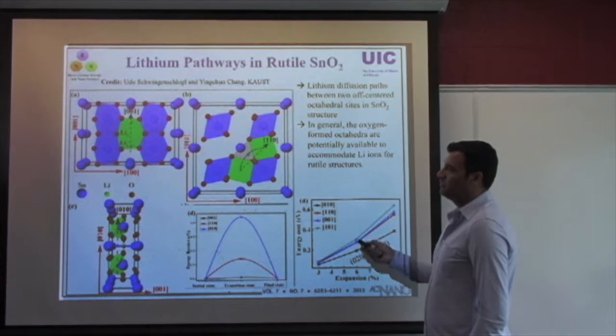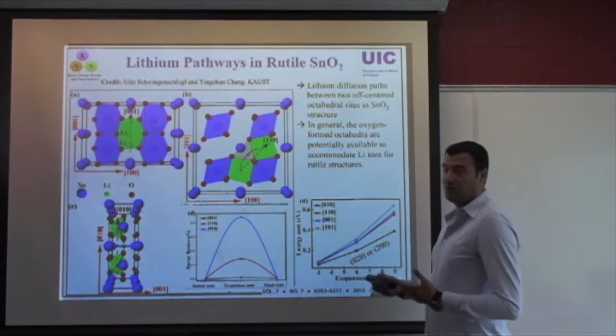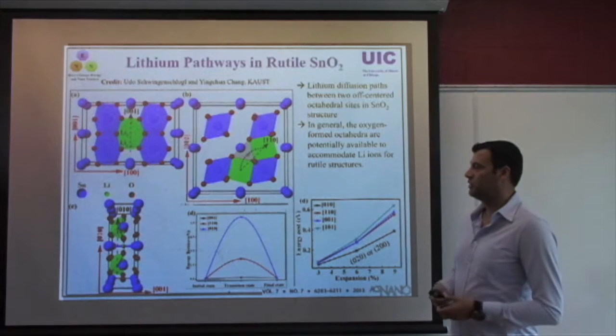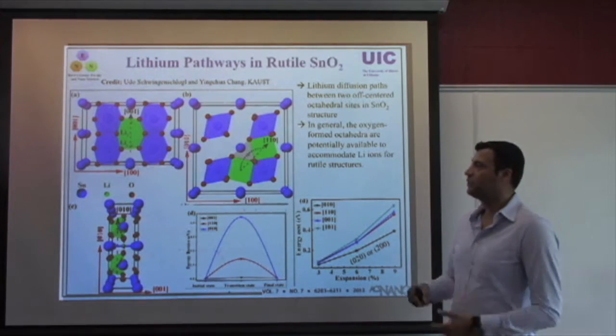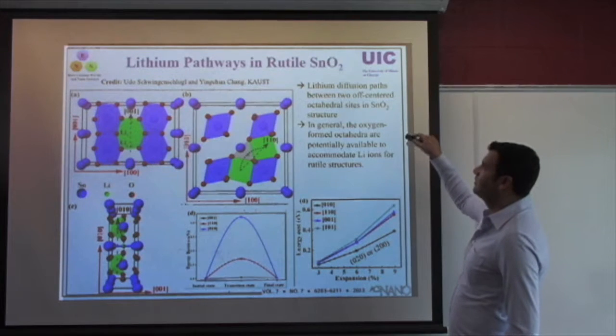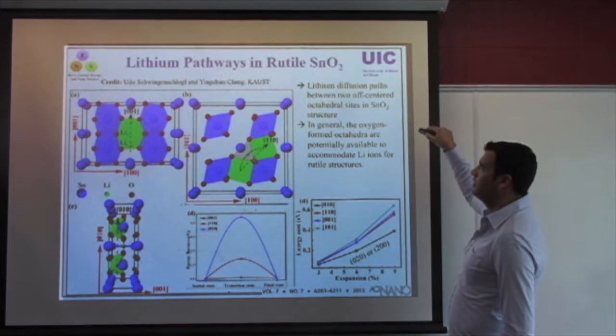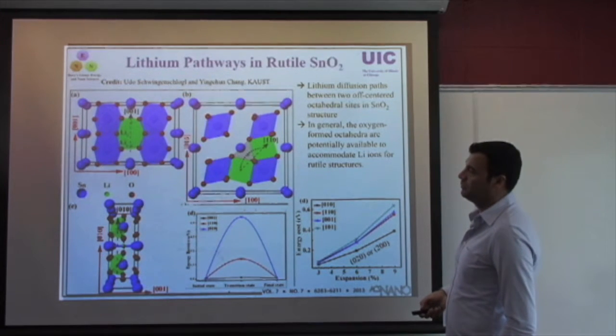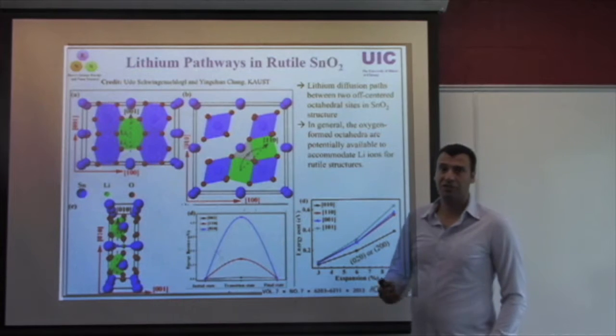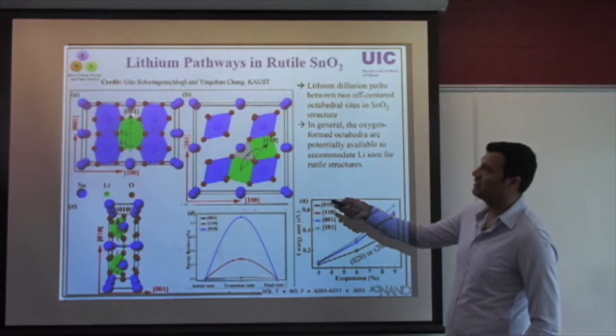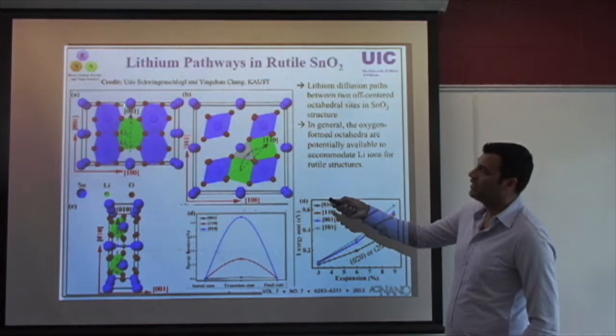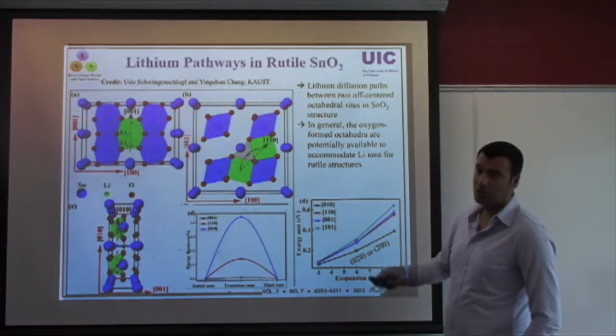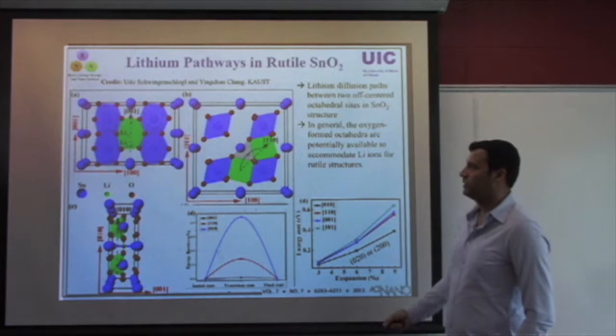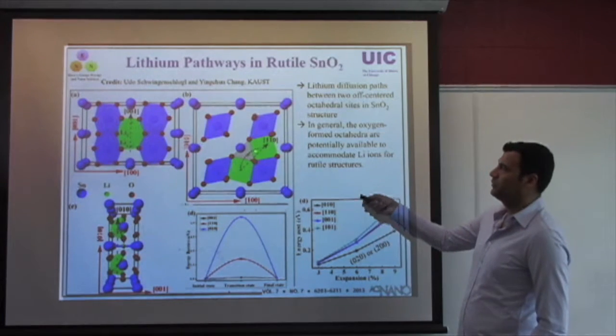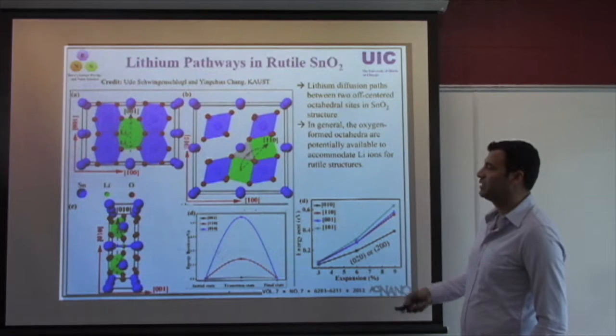We have looked into a variety of ways to explain why diffusion of ions is preferred in one direction versus another, and we are seeing that off-centered octahedral sites in tin oxide are responsible for the change in behavior of lithium ion diffusion. Here we see that along the 001 direction, we get a much lower energy barrier for the diffusion of lithium compared to other directions we see in our samples.